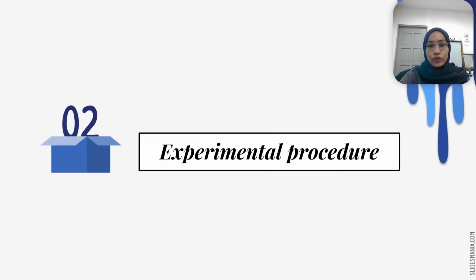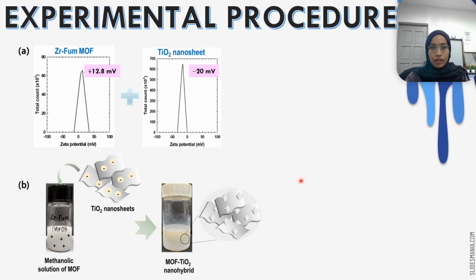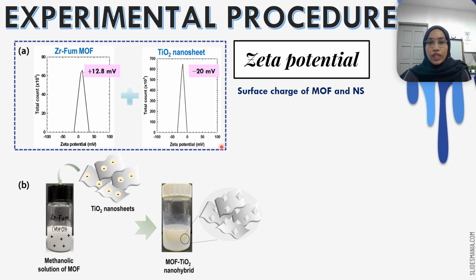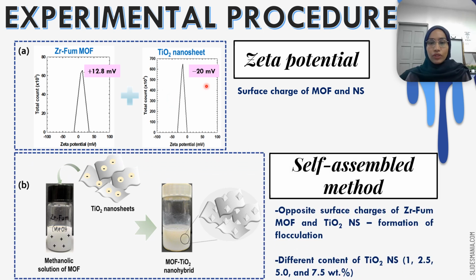Next, we move to the experimental procedure. In my work, I use the zirconium fumarate MOF and also the TiO2 nanosheets. I use zeta potential in order to measure the surface charge of these two materials. As you can see from here, the MOF is positively charged, while the TiO2 nanosheets are negatively charged. So these two materials can be easily mixed together because of the opposite surface charge.